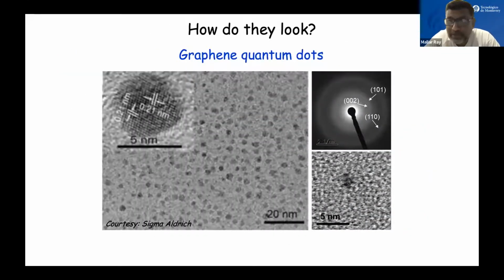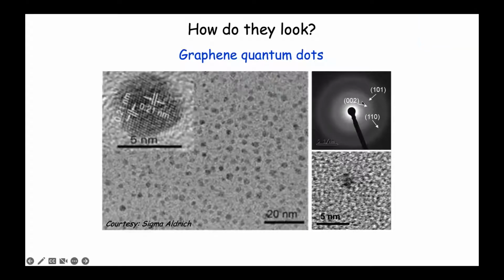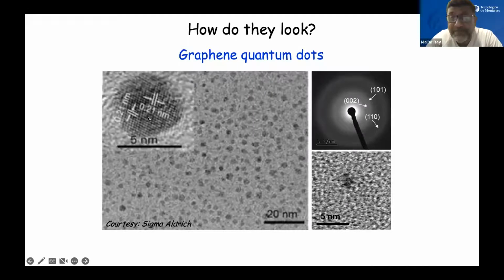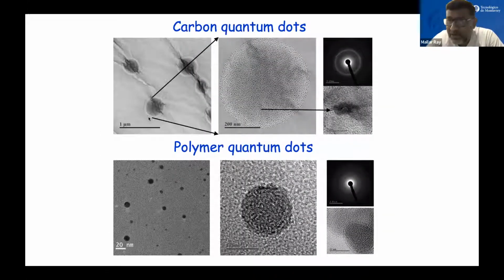But how do they look? If I look at just this bright field micrograph, most of them look very similar under a transmission electron microscope. But a closer inspection of graphene quantum dots would definitely give you a crystalline structure, and the diffraction pattern would give you some diffraction reinforced areas, consisting usually of rings because of randomly oriented nanocrystals. But the essential feature of graphene quantum dots is that they will have some signature of order, crystallinity. The carbon quantum dots, similarly, as I said, are usually larger than the graphene quantum dots because inside them you have small flakes of graphene, and they are crystalline.